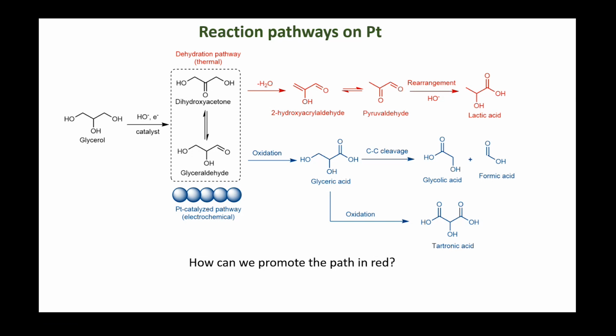And so we knew that we have a pure electrochemical step, which I just showed you previously on platinum and platinum nickel, where basically you get from glycerol to glyceraldehyde, which then is oxidized to glyceric acid, tartronic acid, glycolic acid, and so on. And I showed you that it's actually hard to control the selectivity. However, from thermal catalysis literature, we've learned that if you could actually just turn glycerol into dihydroxyacetone, this dihydroxyacetone will further dehydrate to form 2-hydroxyacrylaldehyde, which is in equilibrium with pyruvaldehyde. And because we are in an alkaline environment, this will rearrange to lactic acid. So we thought, how could we actually promote the path in red?